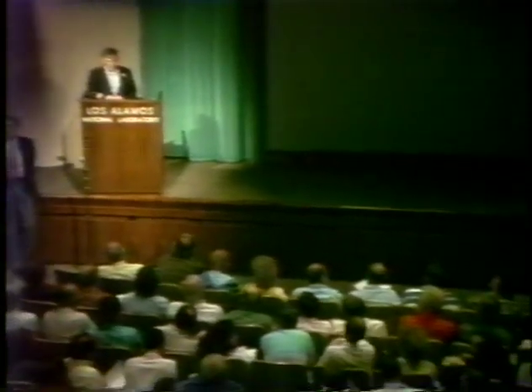Can you describe a little more about the experiment that failed and what you observed when that was concluded and what you did to analyze the results and what you think? Which experiment is that now? The one that vaporized or self-destructed? It was a bit of a mess, to say the least, but that had been running for several months, and we decided to start doing the thermochemistry, so we wanted to turn the cell off. So we turned it off too quickly, and several hours later that accident happened, and it vaporized 90% of the cube and the bottom of the vessel and some of the surrounding materials and equipment in the hood. That was also a cast, by the way.